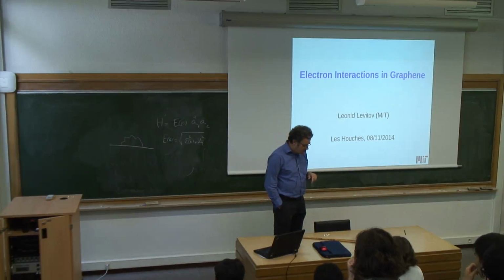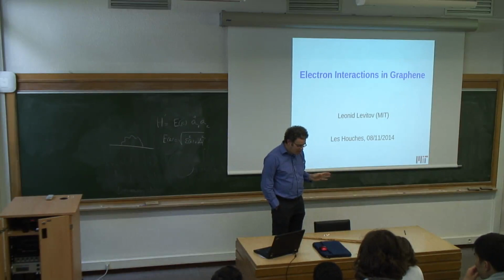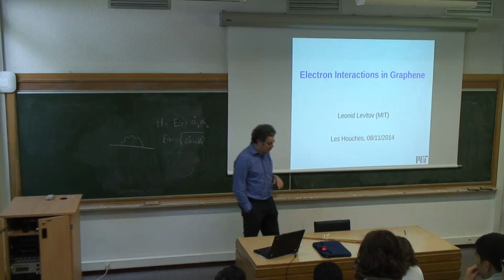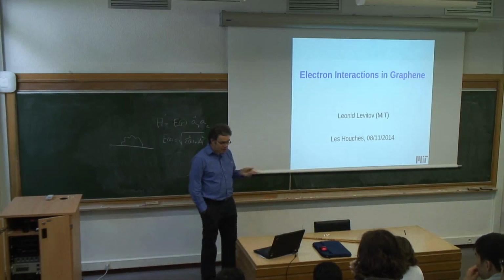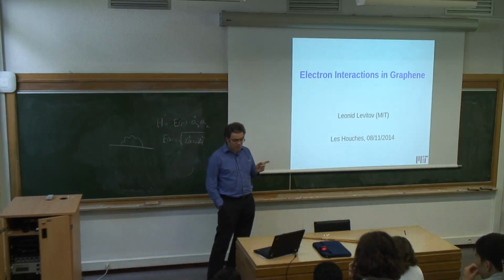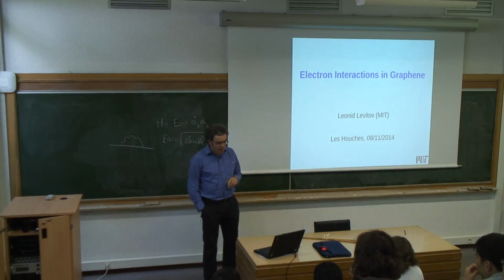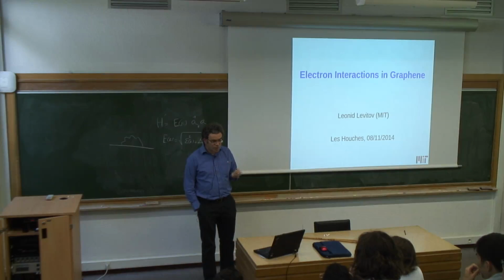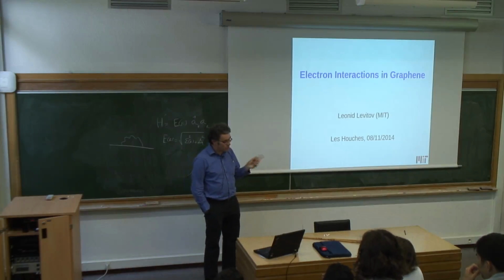Graphene, I think people will try to intercalate graphene. Maybe we'll have more luck with bilayer graphene or trilayer graphene than with single layer graphene, and see if they can get superconductivity along the same lines. Intrinsic electron-phonon interaction in graphene is perhaps very weak, but one can follow several other routes.